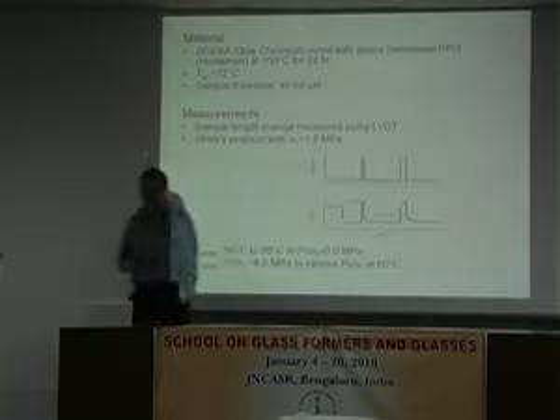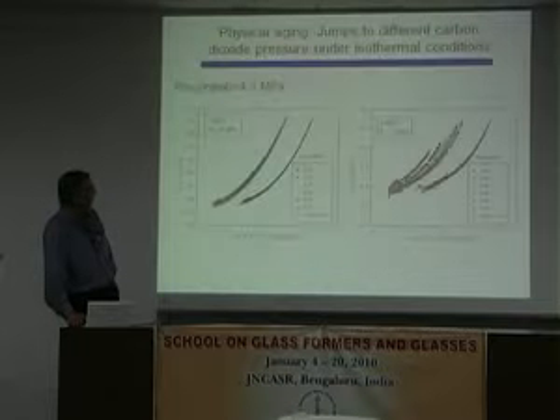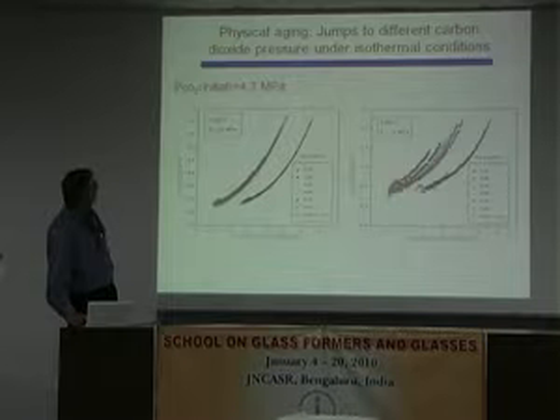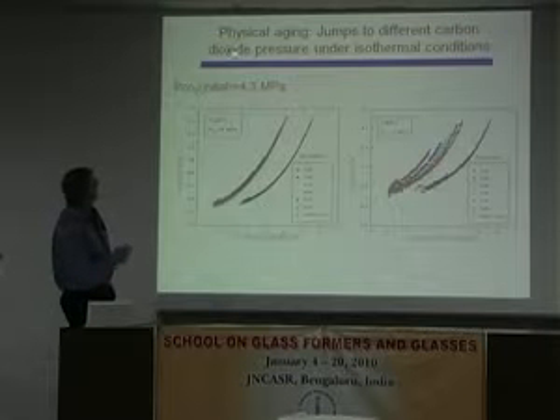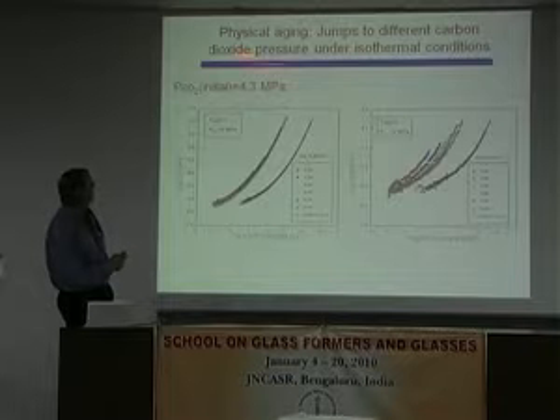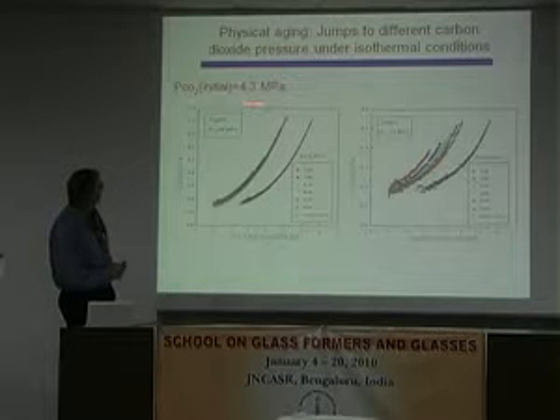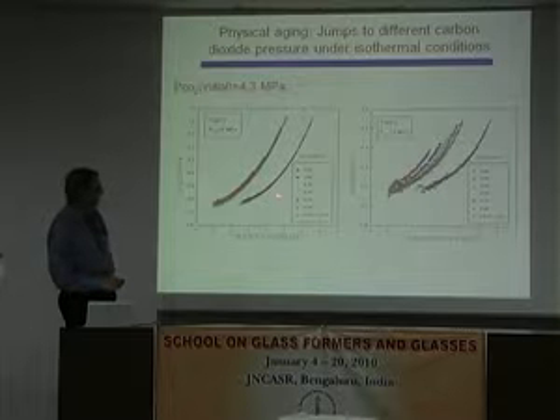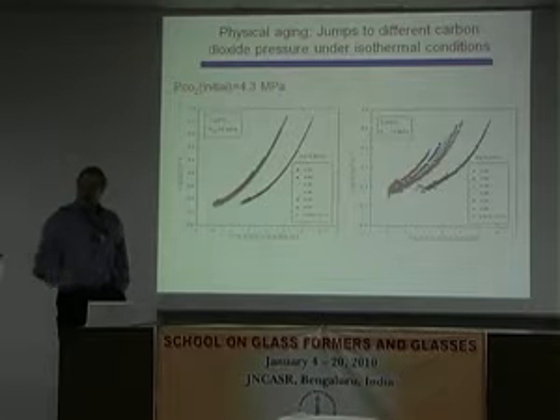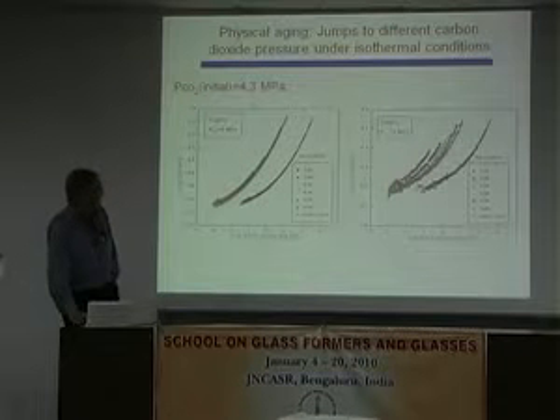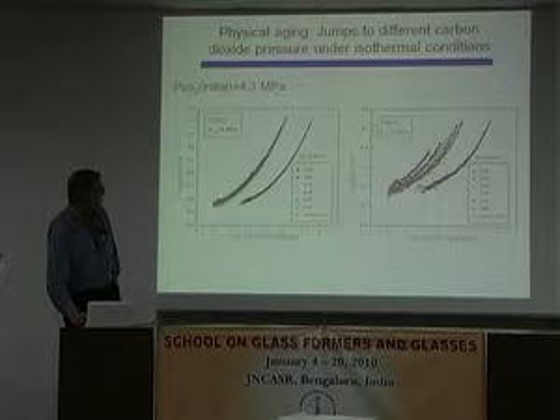Yeah, okay. It's very subtle because it was something that was very unexpected for us, too. So there's something subtle in the structure of the glass that we don't understand. So this just shows we can do different jumps to carbon dioxide pressure here, so we're doing pressure jumps. So we get a plasticizer jump experiment, we get physical aging, and we get time-aging time and time-pressure superposition.